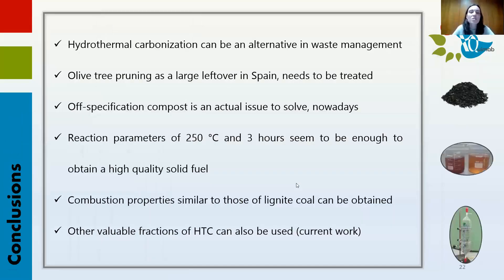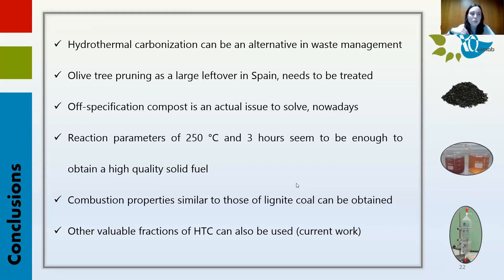Finally, some conclusions from these experiments: HTC can be an alternative in waste management. Olive tree pruning is a large leftover in Spain that needs to be treated, the same as off-specification compost, which is an actual issue to solve nowadays. More related to HTC, reaction parameters of 250 degrees and three hours seem to be enough to obtain a high quality solid fuel with combustion properties similar to those of lignite coal. Other valuable fractions obtained from HTC can be useful not only for energy applications but also for obtaining different products, and this is what we are currently working on.